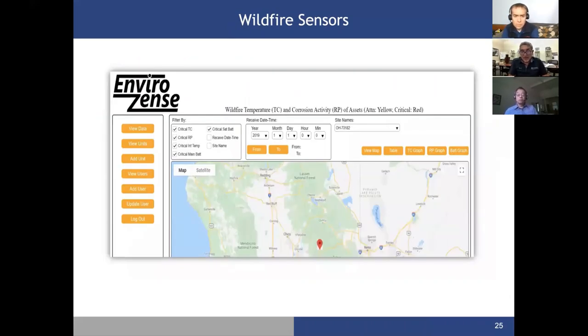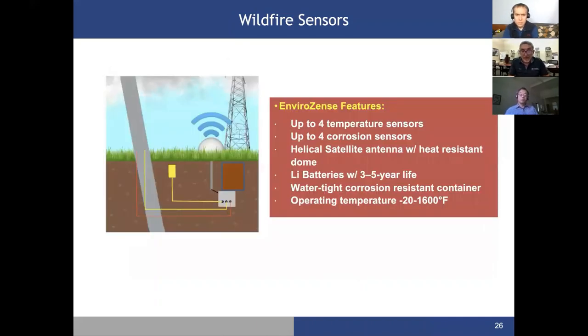These sensors can identify where those structures are. Then they can have up to 4 temperature sensors at different areas of the tower. It can have up to 4 corrosion sensors. The signal will be submitted immediately by satellite to the project owner, and they can last 3 to 5 years. And the operating temperatures could go as high as 1600 degrees Fahrenheit. On the left, you can see a photograph showing one of these sensors.